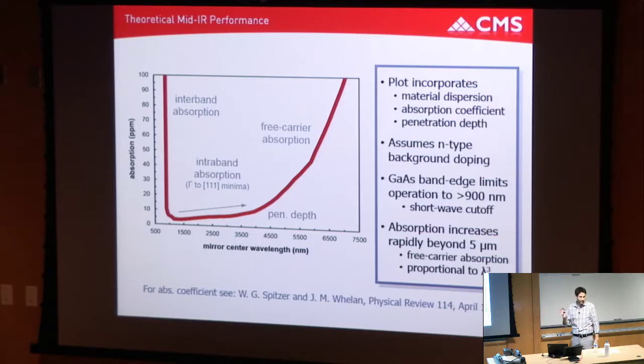The lower you can get the free carrier absorption, the better you're going to be. You can start to pull that arm down. But you can already see those are promising numbers. That's 100 ppm of absorption out to 7.5 microns, which is actually quite good. And you can maintain sub 30, 40, 50, 20 ppm absorption out to 4 or 5 microns, which is extremely nice. You can imagine making 100,000 finesse-type cavities out to 4 or 5 microns.